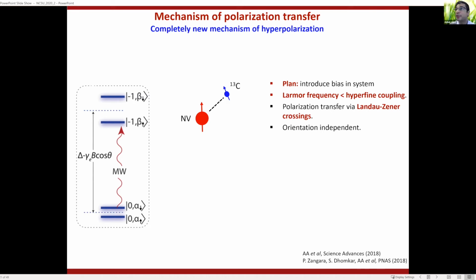This is a very special regime that's opened by these NV centers, and by the fact that you can polarize them at very low magnetic field. So here is an energy level structure of a single NV coupled to a single carbon. This is an electron, this is a nuclear spin. And electronic spins are much larger in energy gap. So you've got the manifold of nuclear spins with the electron at 0. And this is a manifold of the nuclear spins with the electron at -1. But very importantly, this energy gap is smaller than that energy gap.